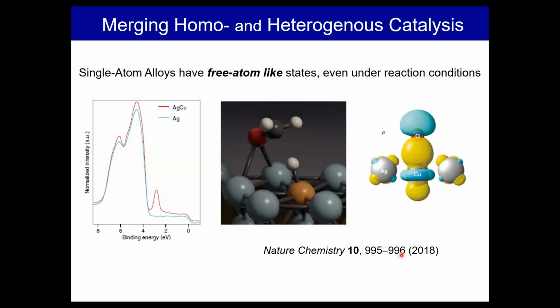So this is a recent paper from Robert Schlögl's group looking at copper atoms in a silver host. And what you can see from the synchrotron XPS is that this is the D band of the silver host. Whereas when you put a single copper atom in, you have a localized copper state. There's very little hybridization of the copper atom with the silver host, which means the electronic structure of this copper atom looks much more like a copper atom in a vacuum than it does a copper in a copper metal.